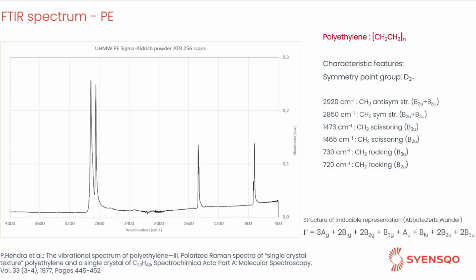On the other side, here is an example of a polyethylene material. It is a very well known and simple spectrum, even considering the fact that despite its simplicity, it has been a subject of debate during the 70s for the right interpretation of all the features and the small features of this infrared spectrum. Here are indicated the normal modes with the main assignment, and the symmetry point group of the polymer chain backbone of the structure of polyethylene is D2H. Here you can observe how the intensity of the CH stretching is, in this case, dominating the whole infrared spectrum.